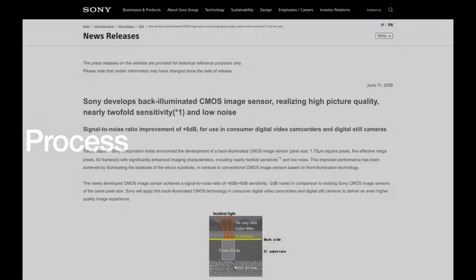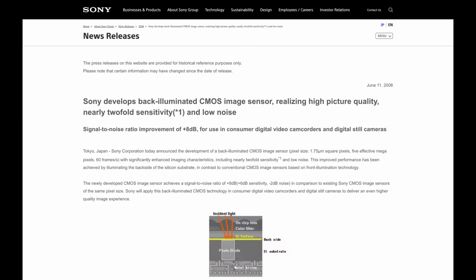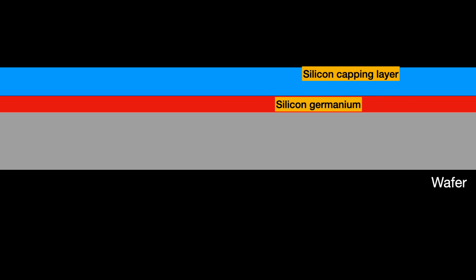It can be done, but what IMEC is proposing has some tricky new things to it. Rather than 5 to 10 micrometers that Sony did, we need to thin out the silicon wafers to 500 nanometers, or just 0.5 micrometers. This is way far beyond what Sony was doing 15 years ago. You start with an ordinary wafer. Then you grow 2 layers on top of it, a 50 nanometer thick layer of silicon germanium, and then a second, thicker capping layer of very pure silicon. This capping layer is where we then cut our buried power rails using the aforementioned shallow trench isolation technique. We also use ALD here to metallize the trench with tungsten or ruthenium.